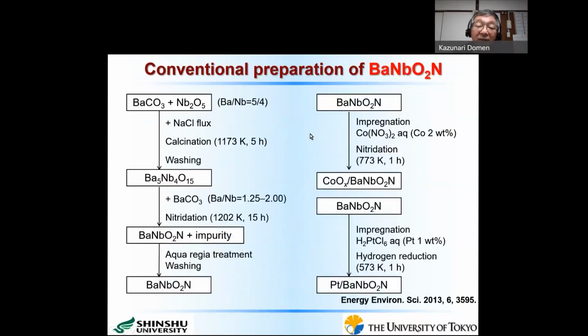And then let me just discuss a little bit about niobium-based photocatalysts, in this case, barium niobium oxynitride materials. You don't need to follow the detail of this complicated feature, but we use niobium pentoxide, then mixed with barium carbonate, then we prepare the barium niobium oxide, then we nitride using ammonia to produce the barium niobium oxynitride as shown here. And then we further modify this barium niobium oxynitride by modifying cobalt oxide. In this particular case, we use this material as O2 evolution photocatalyst.